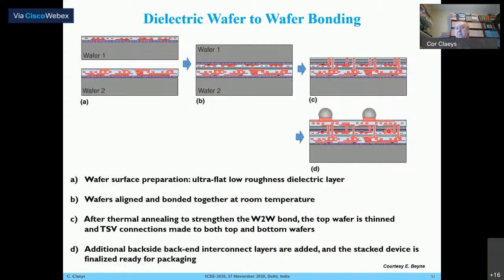And one way to do that is, for instance, to work with dielectric wafer-to-wafer bonding. You have two different wafers with two different functionalities, different types of processing. You do a room temperature wafer bonding. You do a temperature step to improve the bond strength. And then you're thinning the wafer, and then you're doing through silicon vias. And finally, you do the final packaging.